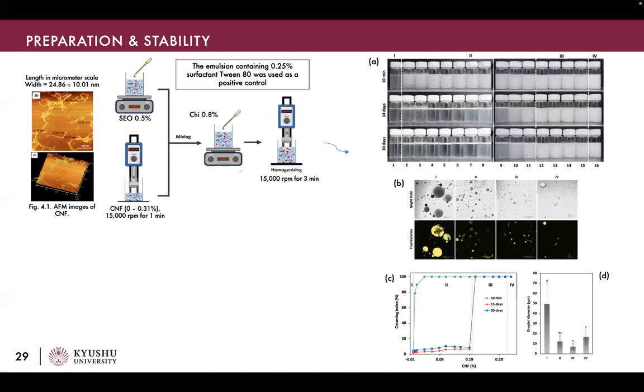And then the second group, the emulsion was not stable and clearly split into 2 different phases. And group 3 demonstrated the absence of creaming index, which was the same as group 4, which was a regular emulsion. The morphology and droplet size of oil was investigated by using CLSM, and its results suggested that the incorporation of 0.24% of cellulose nanofiber may be an ideal stabilizer candidate.